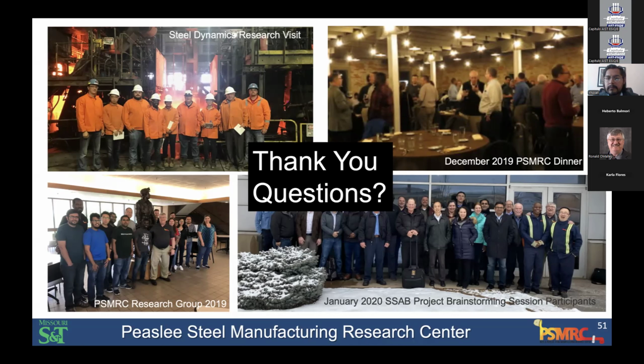That's excellent. Do you have any ideas for the methods that you may use to increase stirring during the process? Yeah, so I have a couple of different views on that. One is that there are big differences in stirring in general between AC and DC EAFs. And I am a fan of DC EAFs because the current flow through the bath actually induces stirring and enhances some of that mixing that you need in the process.